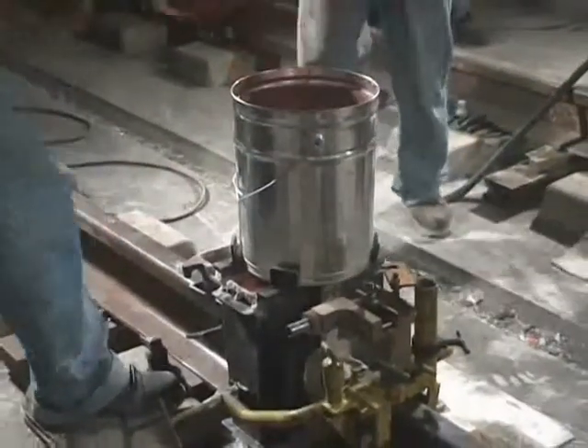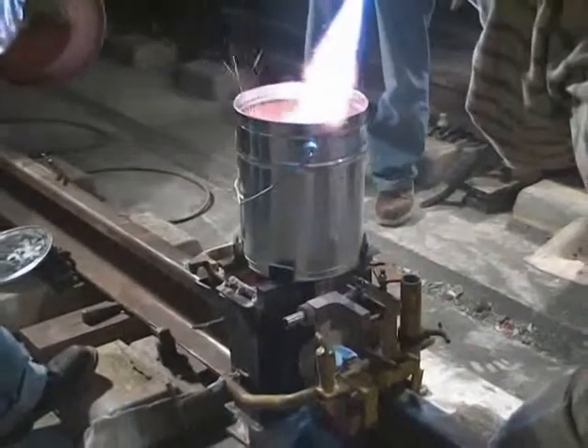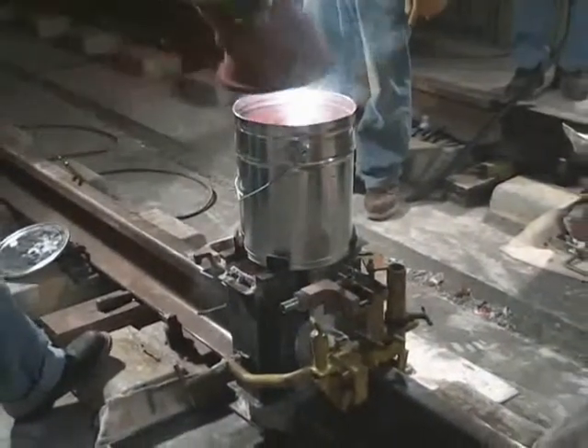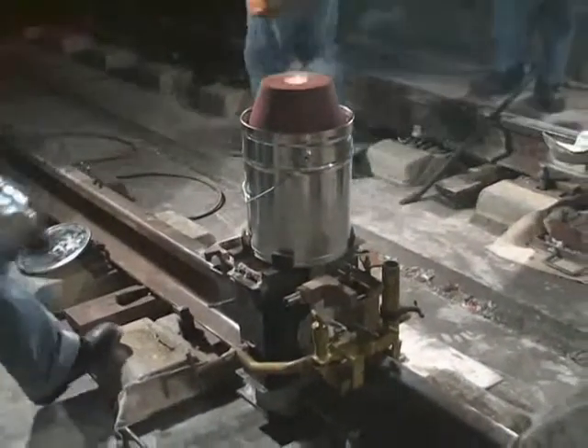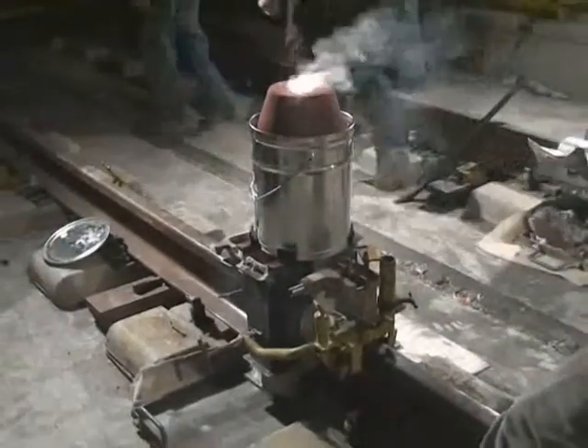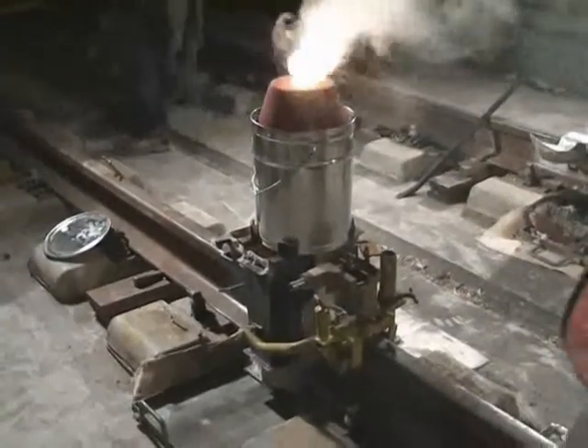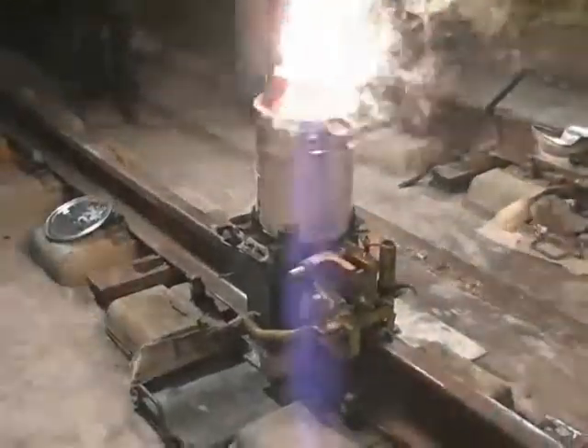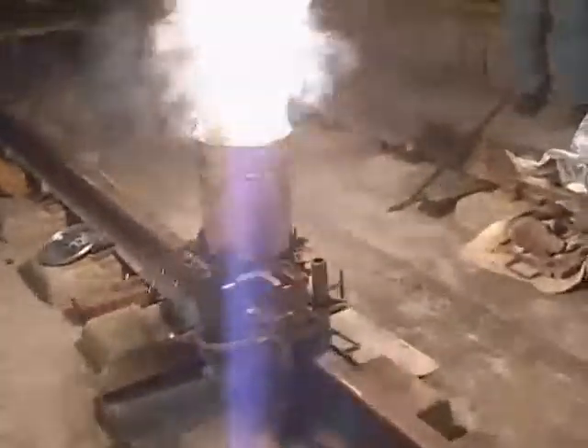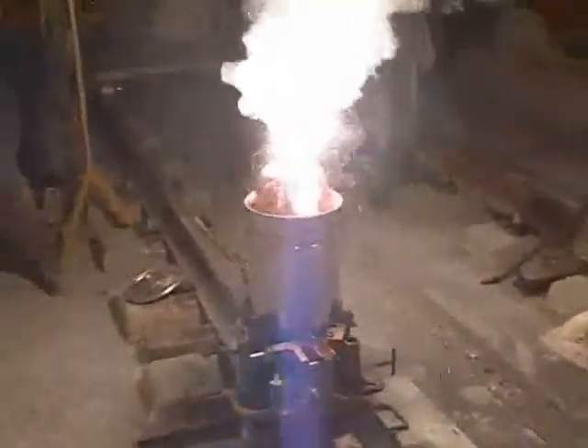At the prescribed time, a crucible loaded with the thermit portion is ignited above the mould. This reaction reaches temperatures of more than 1000 degrees Celsius before a special heat-activated thimble at the base of the crucible liquefies and the portion flows down into the mould.